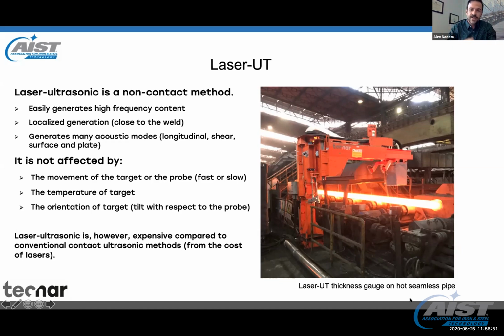As you can see on the right, that's a Technar laser UT system. It's very bulky because it's made to be super robust. We installed those systems in seamless pipelines, and we measure the thickness and eccentricity of the hot pipes actually after elongators, piercing, or sizing mills. And this goes through up to 50 millimeter of steel at 1,000 degrees Celsius. So, I mean, it's an industrial technology, and it can be miniaturized to be quite small. In this case, there's space, doesn't matter, but it's an example of an industrial laser UT application.